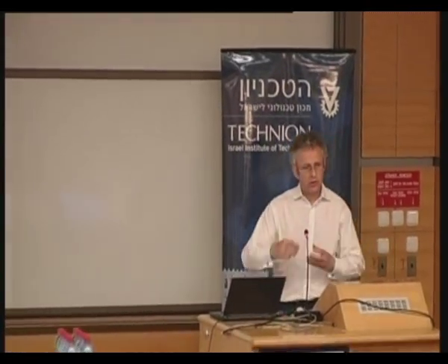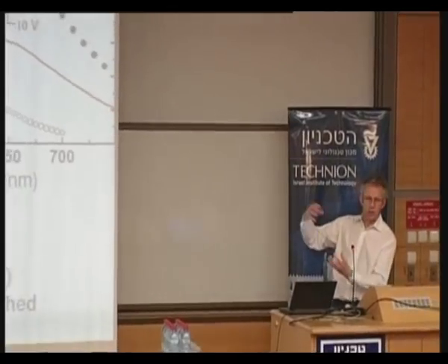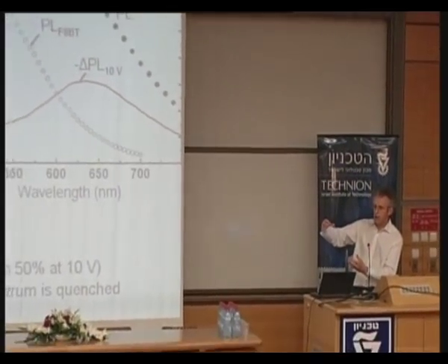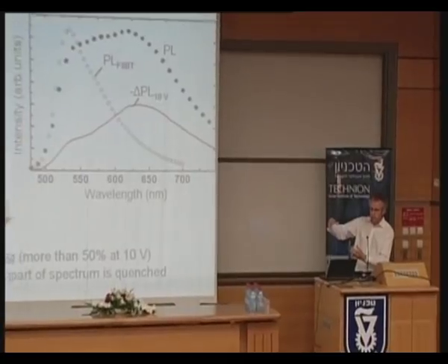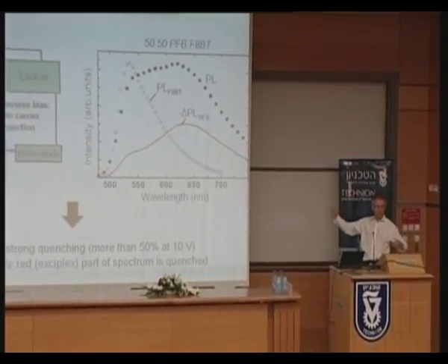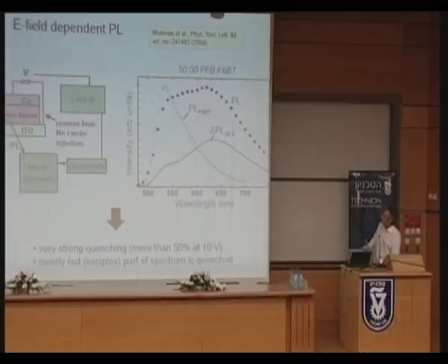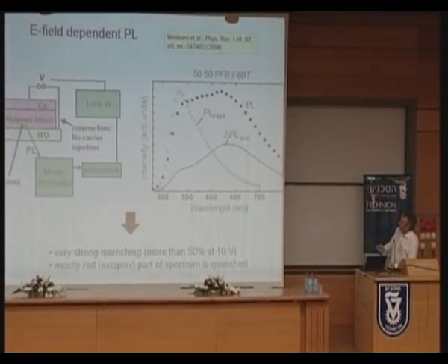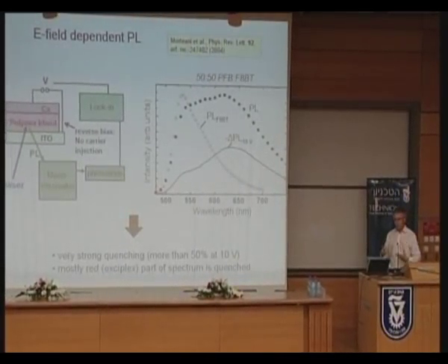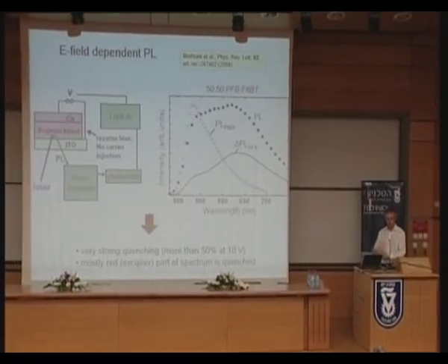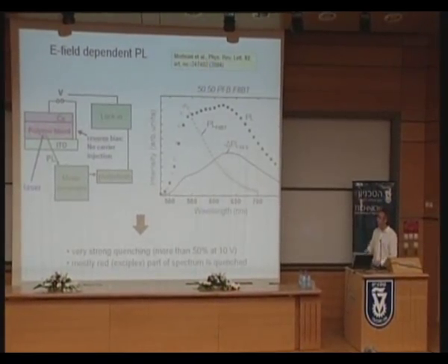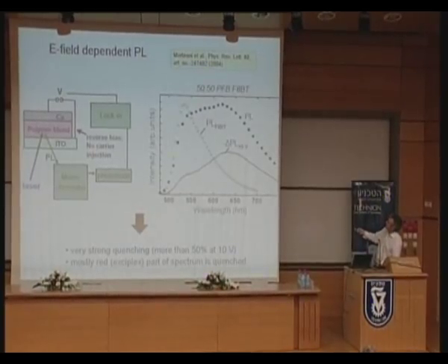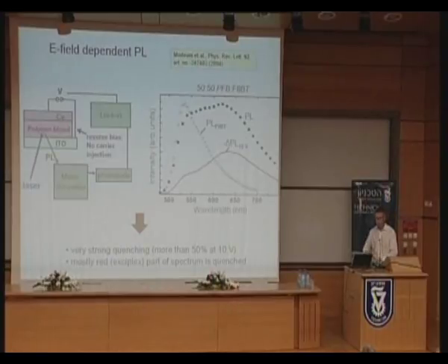Well, you might think that if we've managed to get the charge separation across the junction, it wouldn't be that hard to then put a bit of electric field on and further pull them away from one another. And if you look casually at what's going on, one can see very strong electric field quenching of the heterojunction red luminescence. So what we've done here is just put the sample, the polymer film, between two electrodes and then put a modulating voltage across it and look for a modulation in the luminescence.